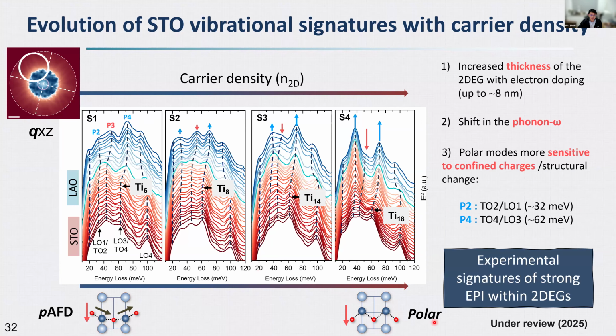And again, if we assign different modes, what we label P2 and P4 in the literature are polar modes introduced by the polar distortion related to the optical phonon. And for these two modes, the energy shift and the intensity increase are more pronounced at higher charge doping and more pronounced when you go towards the interface compared with the bulk. So that's an indication that the polar modes are very sensitive to the confined charge at the two-dimensional electron gas at the interface.